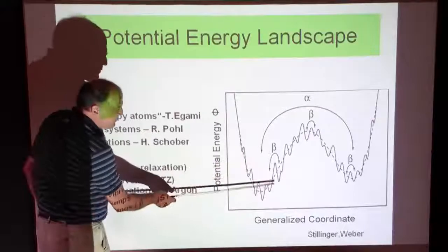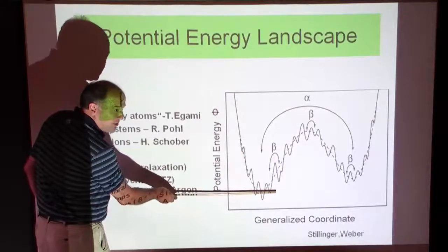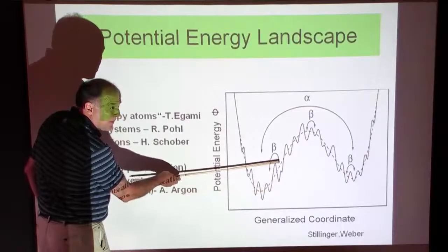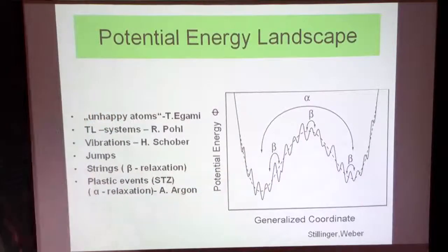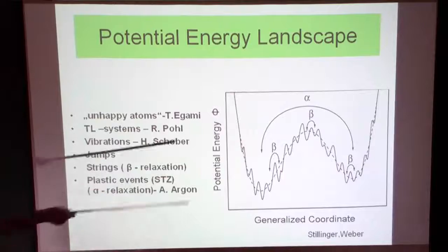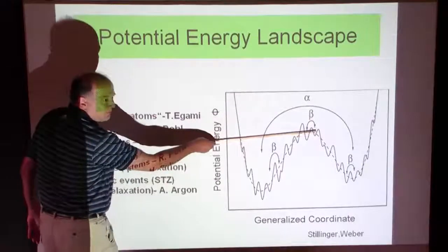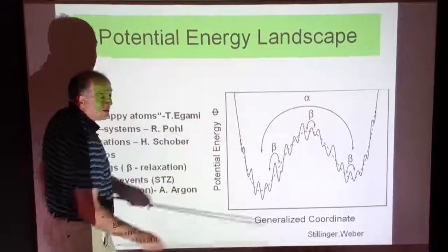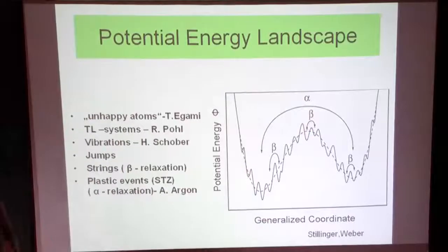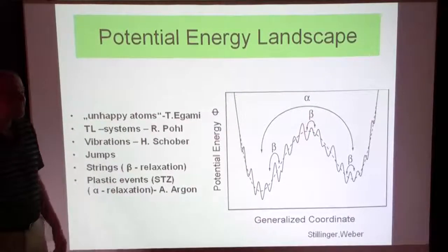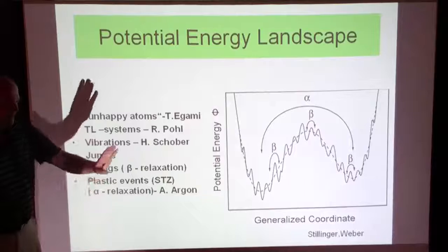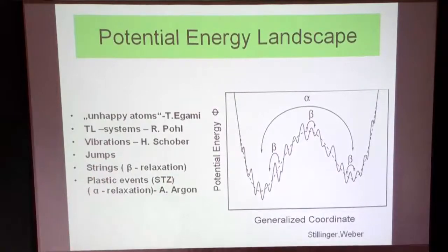So when you want numbers? No, I just want to compare kBT with the height of this barrier. Yes, this is about kBTg. Okay, this is about the temperature of where the glass is. I understand, but your experiment is then typically done at much lower temperature. Much lower temperature, and close to Tg. I will show it to you. What sets the two scales? I mean, now you're postulating one scale for alpha and one for beta, and more or less nothing in between.